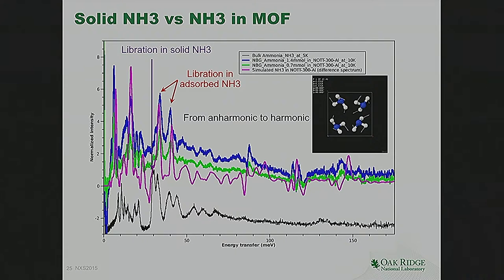And this is curious because I did this experiment when I looked at a very interesting material called lithium ammoniate. I don't have the slide in here, unfortunately, but this is a very beautiful material. It's called an expanded metal. If you go below 80 Kelvin, the eutectic point, it suddenly turns into a metal, and it goes from blue into deep gold color, and essentially it expands itself by a factor of 2. It's actually the lightest metal that we know.